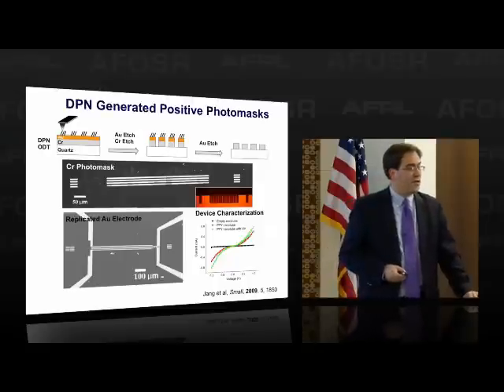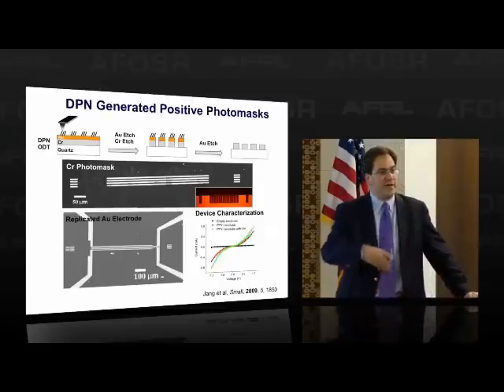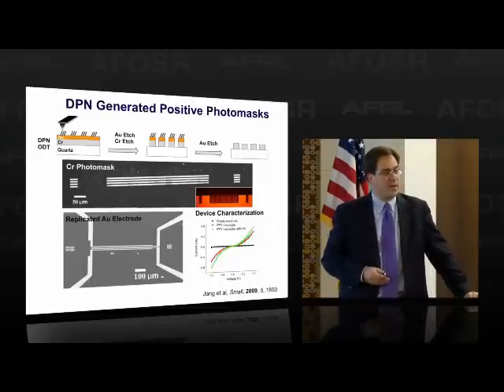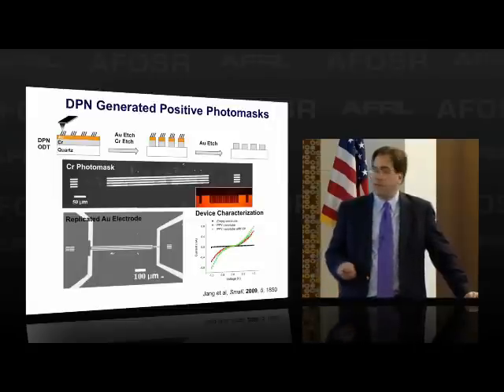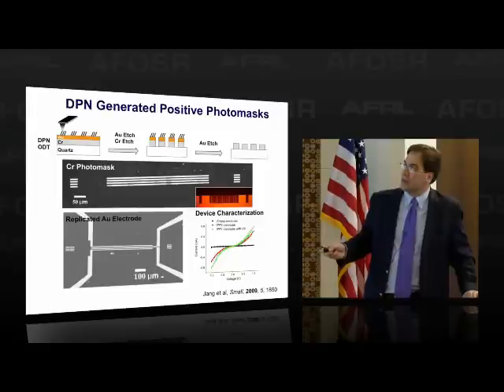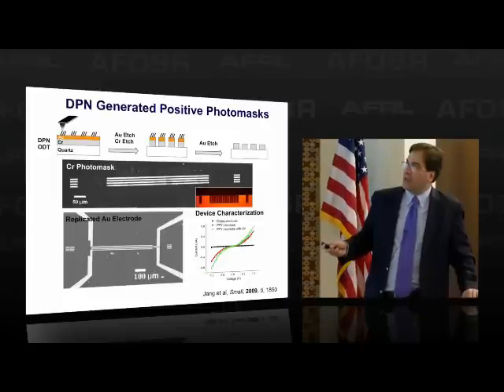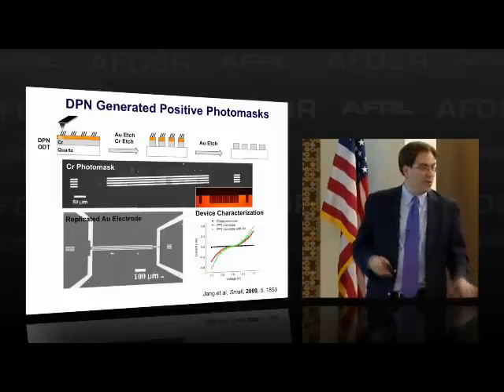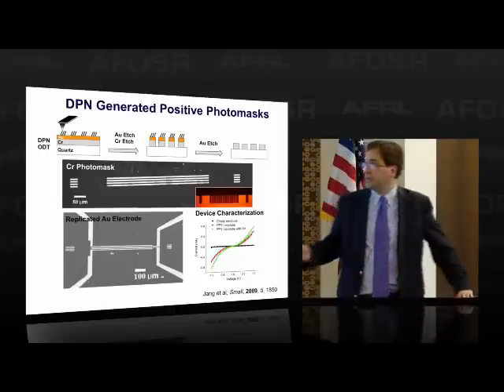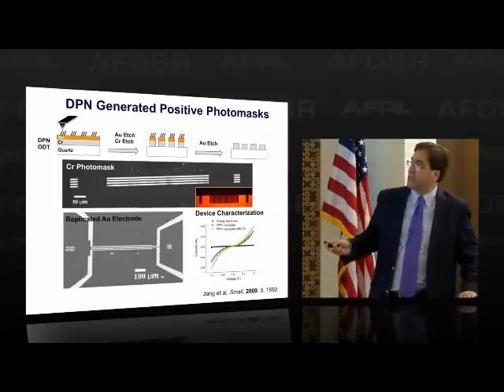You can make integrated electronics as well. So we're not making arrays yet of integrated electronics, but we are making masks. And the way we do that is we take a quartz substrate. Usually you have chromium on quartz as your mask. We put down a layer of chromium, a layer of gold, and then we pattern on the gold alkane thiols that define the pattern that we want to make up our photomask, for example. In this case, it's interdigitated electrodes. We then etch the gold and the chromium. We remove the gold through a gold etch and the molecules, and then what we're left with is this type of structure, a simple photomask for interdigitated electrodes.